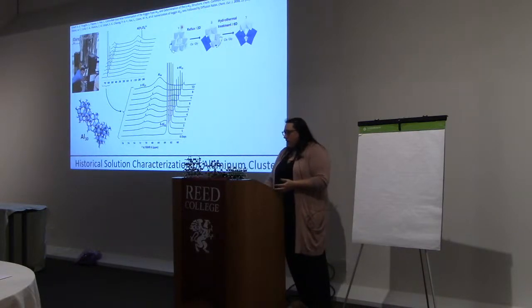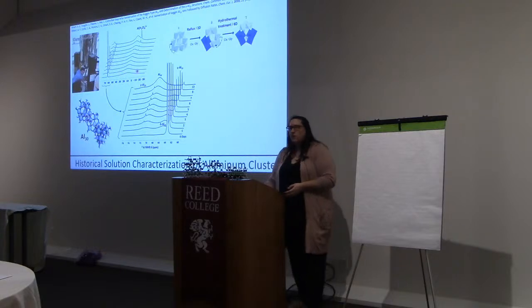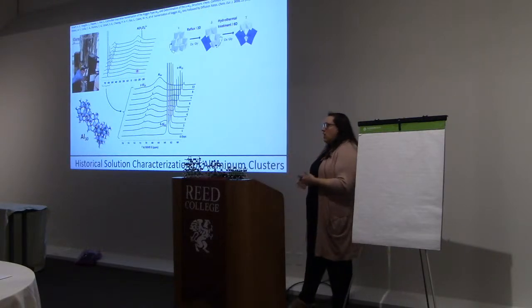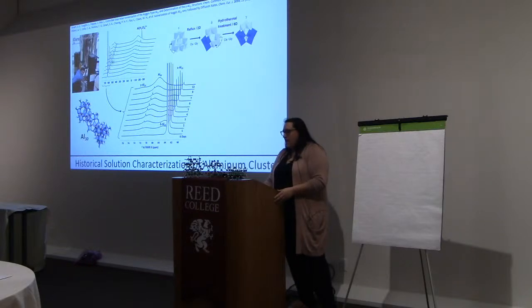And so we were taking our epsilon aluminum 13, dissolving that into solution. This is aluminum NMR. So here is our full spectrum aluminum NMR. This region down here around 0 is where octahedral aluminums show up. There's not much information we can gain in that region. But down here, between 60 and 80, we have our tetrahedral aluminum.